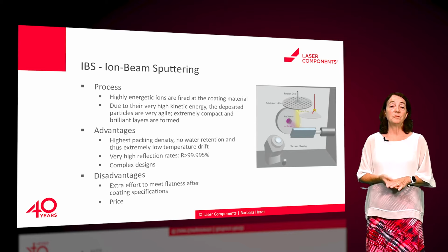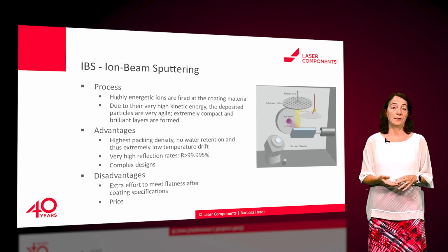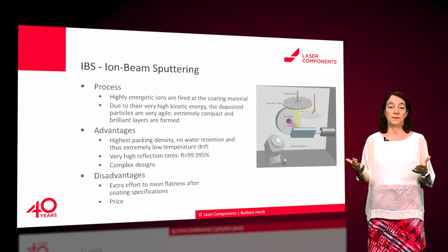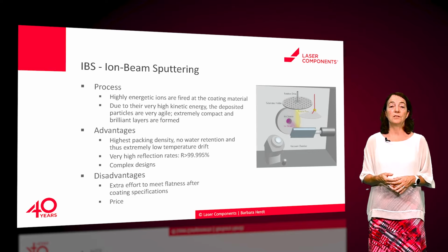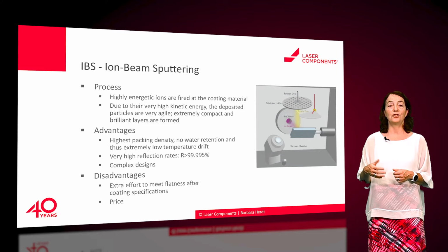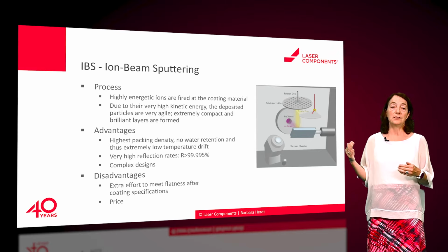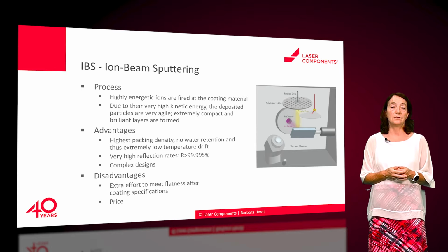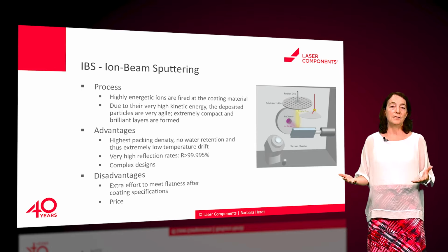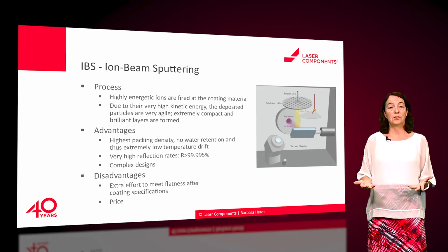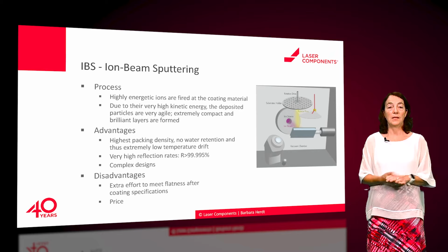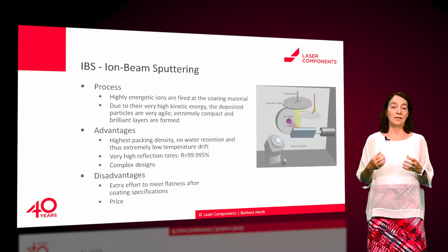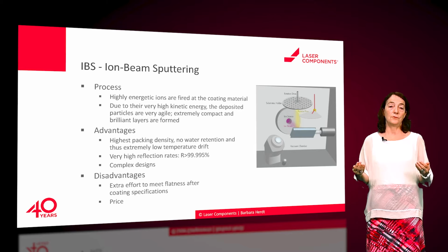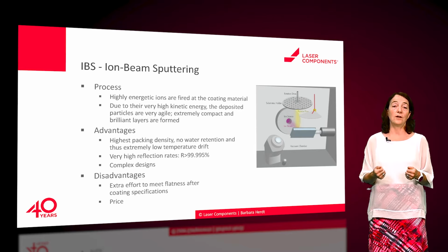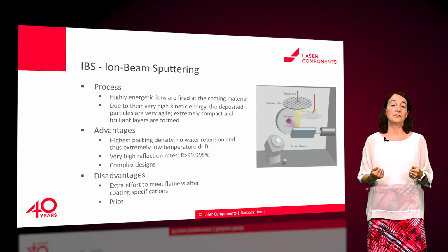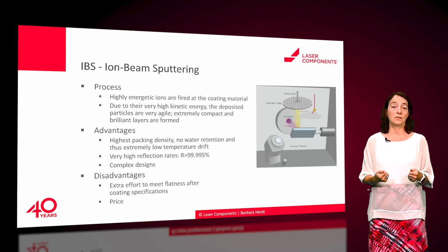Now, IBS or ion beam sputtering could be a good choice in the case of thick layers are needed. This is a completely different process. Here we start with a rigid coating material which is sputtered with a high energy ion beam. The coating material is then accelerated with very high energy on the substrates. This is comparable to IAD, and again, one of the advantages and disadvantages at the same time. The high energy allows a high packing density and thus no thermal drift of the coating, but at the same time a high stress on the substrates, which needs to be compensated with extra effort if the flatness is critical for the application.